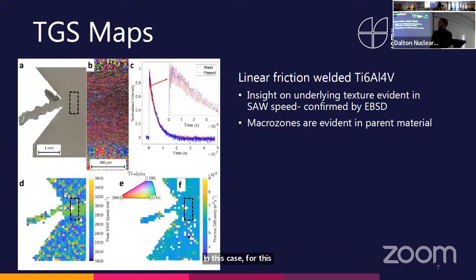This is another map for a friction welded titanium alloy, which was from folks in materials, where two bits of titanium alloy were rubbed against each other basically till they fused. And this is your weld region, and this is your parent material. They looked at EBSDs, which showed a highly textured weld region and a quite anisotropic parent.